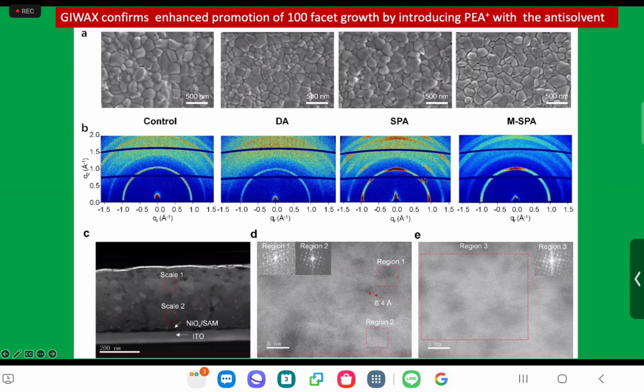So if you look in the GIWAXS, you see control, and this is a 100. This is the 100 circle. And so we see that nothing happens much with the DA. There's some reflections here, but then with the SPA, that means we have not used methyl ammonium, we have used formamidinium. So you get some nice Bragg reflections. But then if you use the methyl ammonium, you get just one peak, believe it or not, and it's at the lattice vector 0. That means you have vertical orientation.